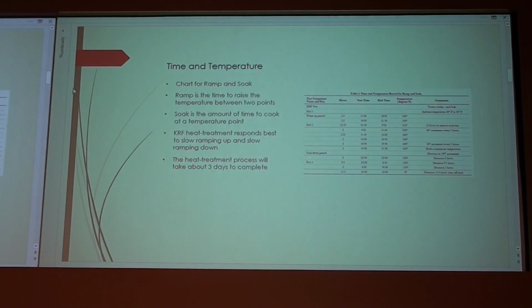So what I did is I came up with a best formula for heat, and this chart is the ramp and soak. Ramp is the raising of the heat level at a certain interval, and soak is how long you leave it at that interval to treat it. And that can vary. Knife River Flint, I found, responds best to slow ramping up and slow ramping down. It takes about 3 days to complete a heating cycle from when it's first put in there until you take it out.